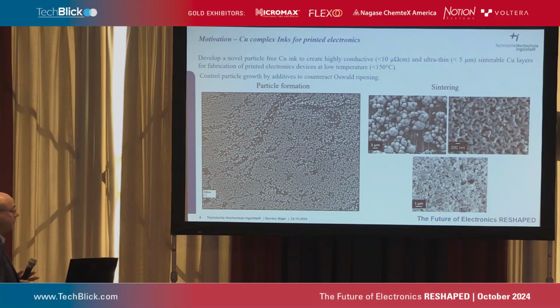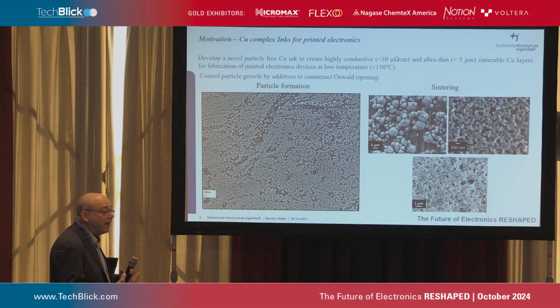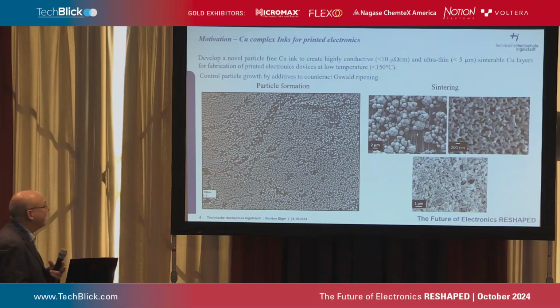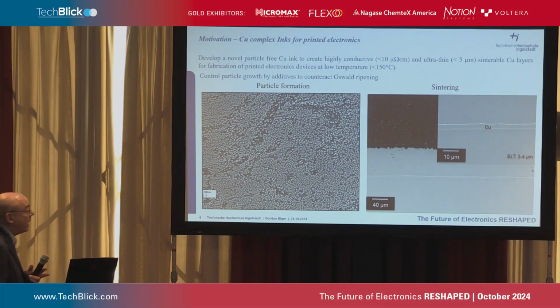In principle, there is the Ostwald ripening, where the small particles form large particles, and then you end up with a large particle. So in the end, you have to fight the Ostwald ripening law to keep your particles small. How do you do it? You do it with stabilizers, which are blocking the growth of the particles. Then we can use it in printed electronics as paste, or we use it also for die attach. Therefore, you apply the ink, you form the particles, and then you sinter a die onto that thin layer.